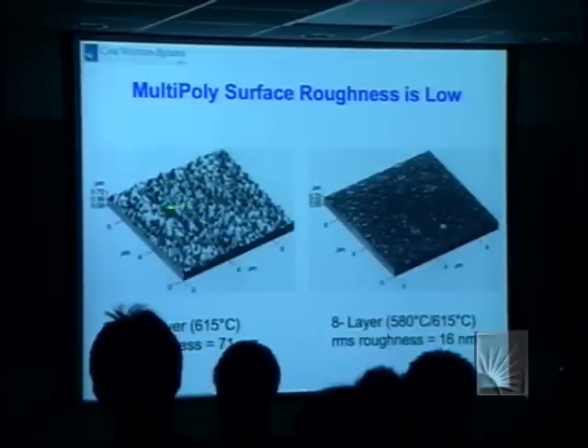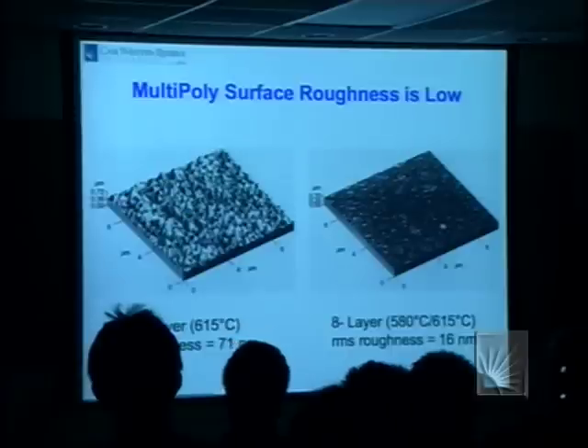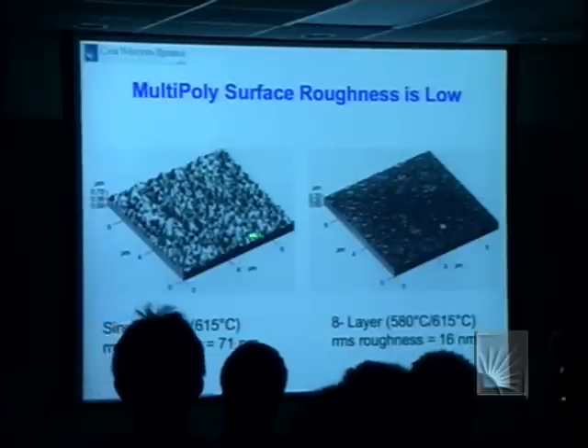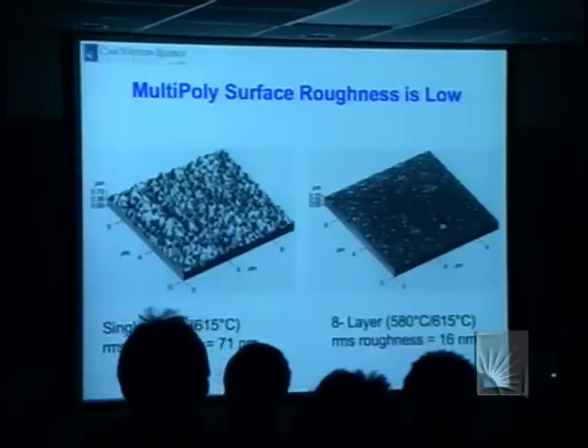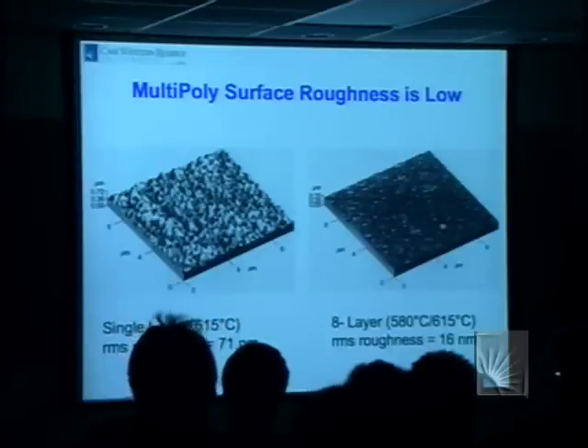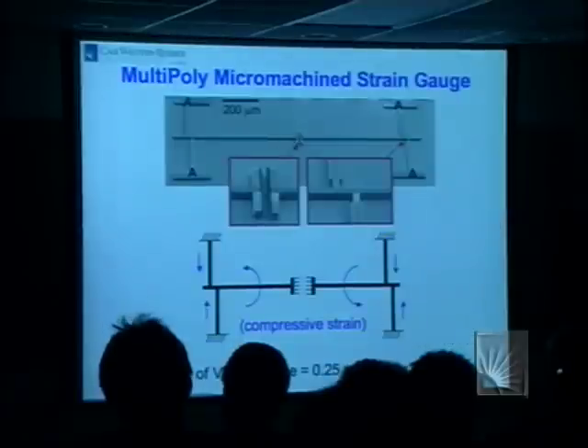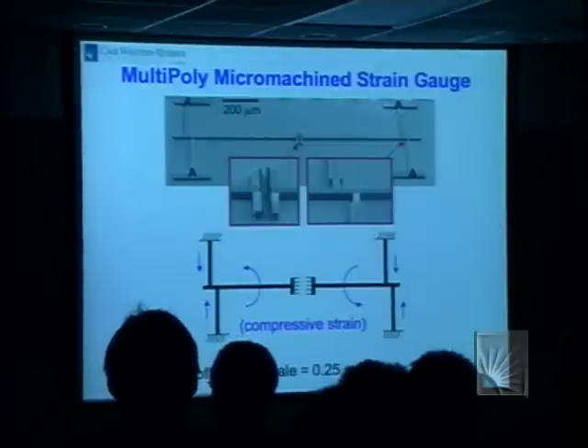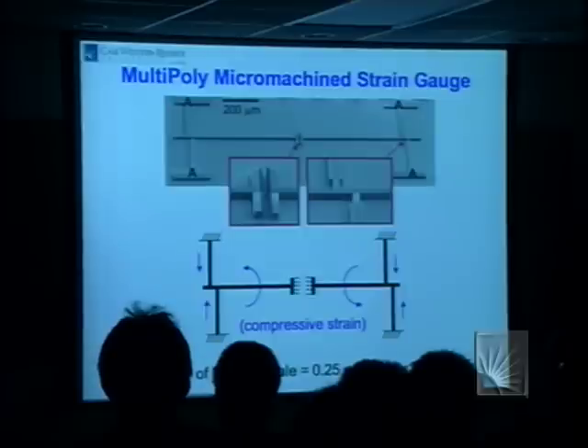Since you limit the extent of the columnar deposition by this alternating amorphous and crystalline material, we get the multi-poly surface has a much improved surface roughness. But what's really important about this process is, as far as we can tell, we can make arbitrarily large devices which are flatter than we can measure.